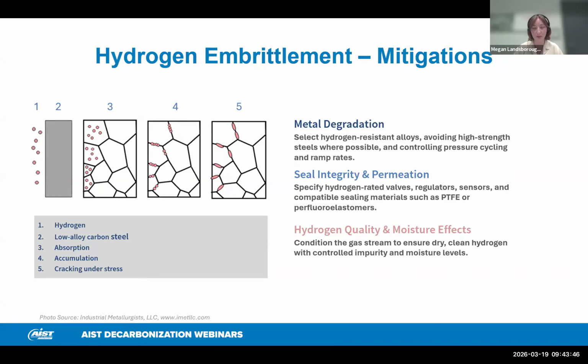So on a project I was actually working on, we needed to specify ethylene propylene for the seal material on all of our check valves, as these seals had the lowest temperature rating at negative 50 degrees Fahrenheit or negative 45 degrees Celsius. And due to hydrogen's properties, we needed to be prepared for the lines icing up or being extremely cold with large amounts of hydrogen ripping through our lines.